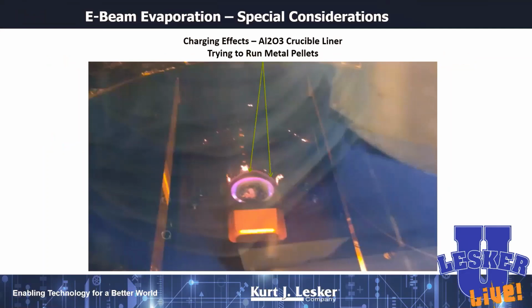Again, I just mentioned these charging effects. So if you're trying to do an electrically conductive material like tungsten or tantalum, don't put it in an aluminum oxide crucible. If you do, when the aluminum oxide crucible charges up, it will start to deflect the beam. And so now the beam won't hit your source material, but it'll hit the gun. And so you'll be depositing the gun. And again, that's considered bad.